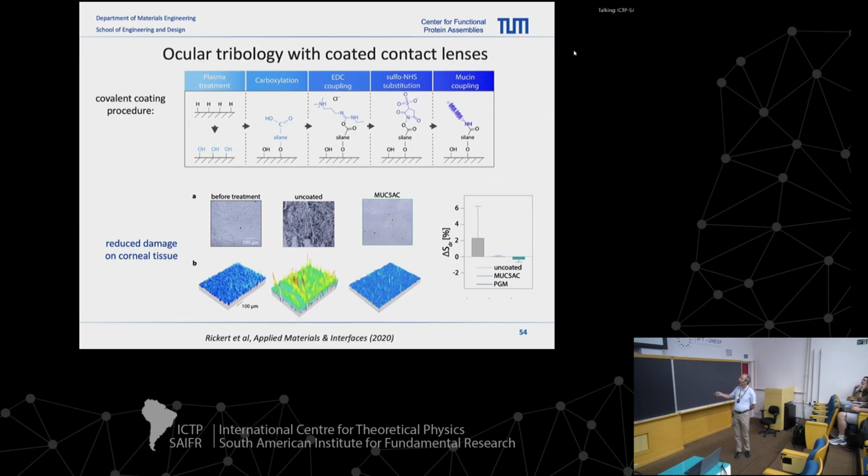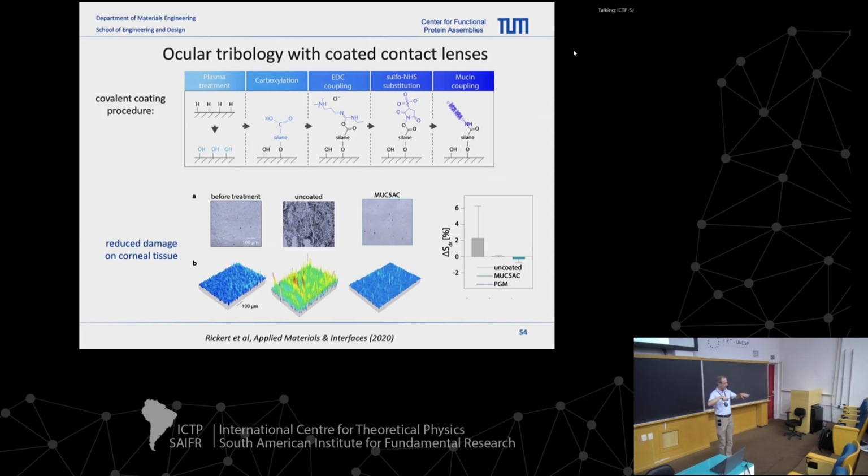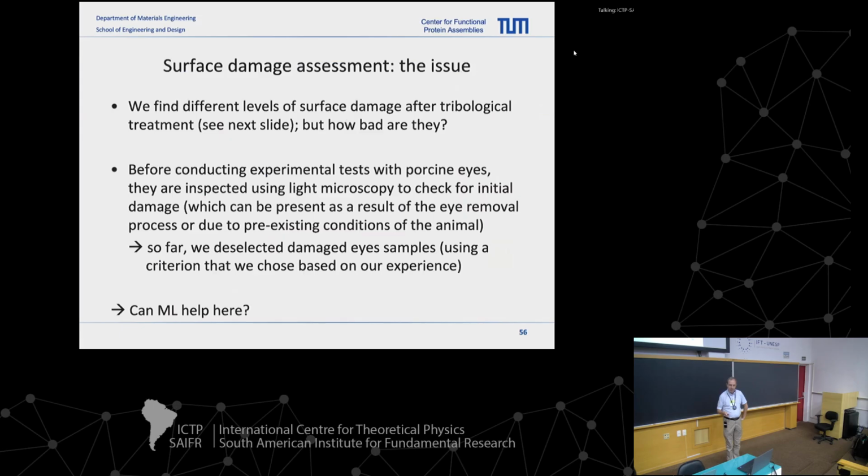them as well. And here you can also quantify this impression with another parameter that we had already yesterday, SDR. That's the total roughness of a surface, right? The net surface divided by the projected substrate surface, and there you see with the coated lenses, there's no increase in surface roughness. So we are very sure that the system works really well. But from a topographical point of view, we have this issue.